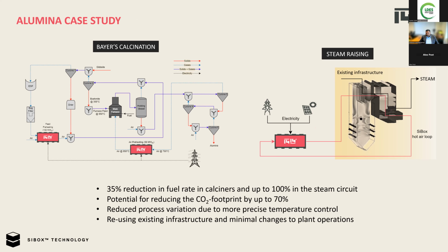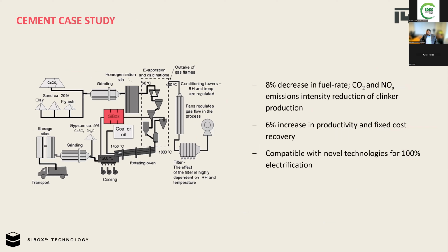What we found using our analysis is that we can replace up to 35% of the fossil fuels going into the calciners and up to 100% in the steam circuit. And this can reduce the CO2 footprint of alumina production by up to 70%. In fact, University of Adelaide, who are part of the HILT CRC, have done this analysis independently as well, and they've come up with even higher numbers for the fossil fuel replacement in the calciner using thermal storage at high enough temperatures. The other industry that we're targeting is cement production.